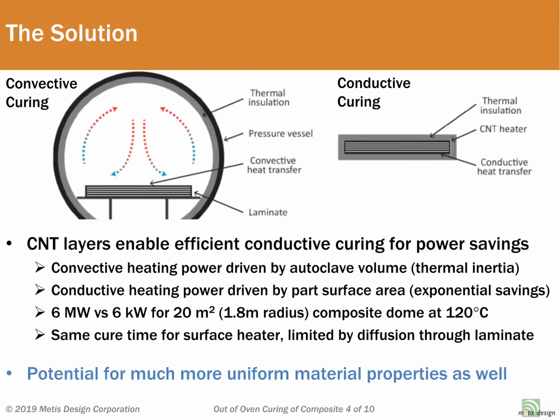Pressure can also be eliminated by removing voids through the control of resin viscosity, which can be achieved effectively since CNT heaters can ramp temperature much more quickly and accurately. As an example case study, for a 1.8 meter semi-spherical dome, such as a radome, an autoclave cure would consume 6 megawatts of power compared to 6 kilowatts consumed in the conductive approach.